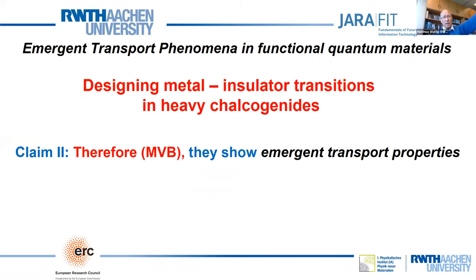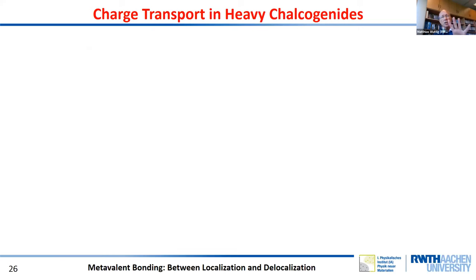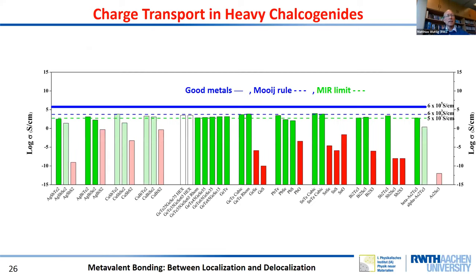So this is now part number two. I hope I'm doing okay with time. So we expect that metavalently bonded materials, this is the name that we give to this green region, should show emergent transport phenomena. And there's a first evidence for this. If we only look at the charge transport in these materials, this is the variation of the conductivity now for a broad range of different chalcogenides. And here as a reference, we have the typical conductivity at room temperature. These are all data for room temperature of a good metal, take silver or copper. This is the conductivity of a good metal.